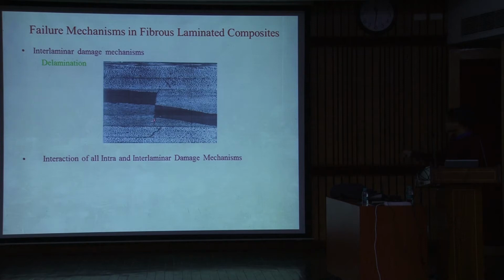And also here you can see, when it was separated, it has seen that there was a weakness in the ply, so it has led to the crack. So these mechanisms are coupled. This matrix transverse cracking can lead to the delamination, or the delamination can lead to matrix transverse cracking. So these are the coupled mechanisms.